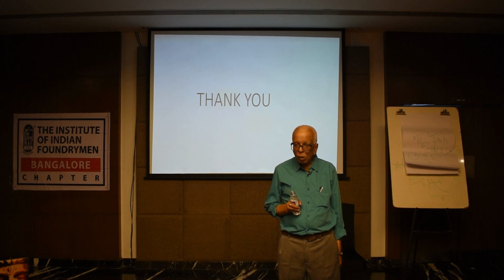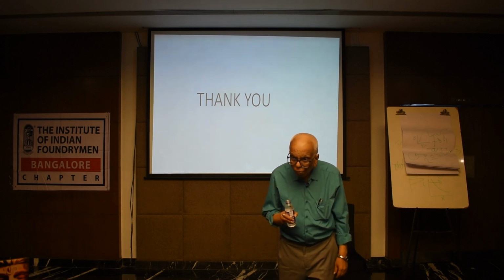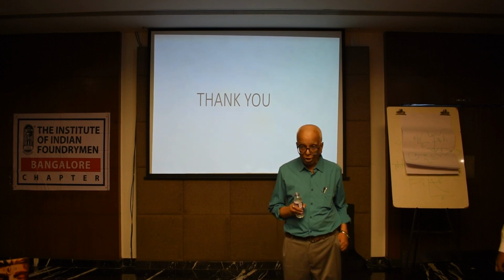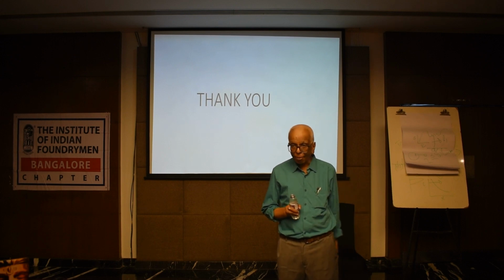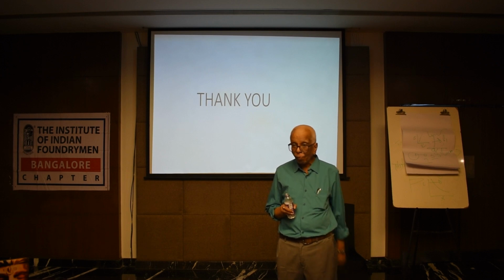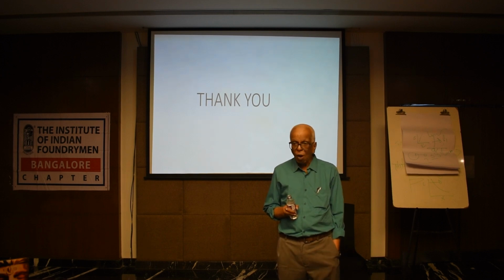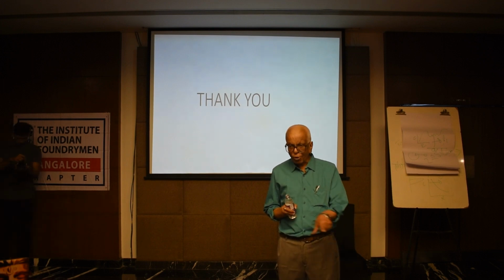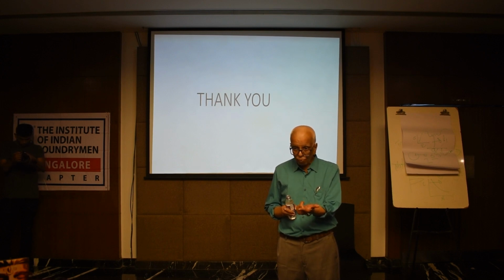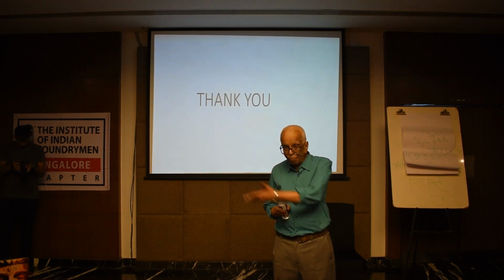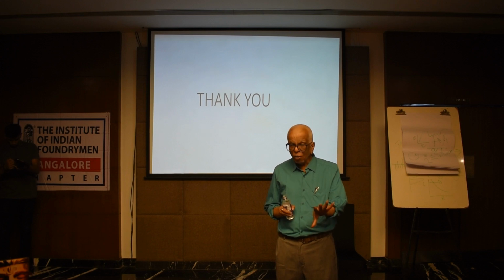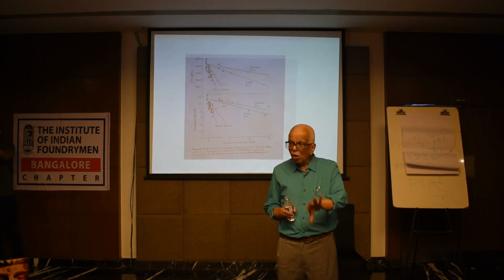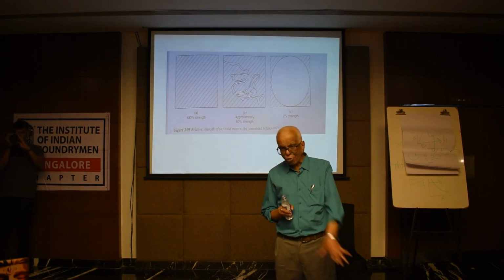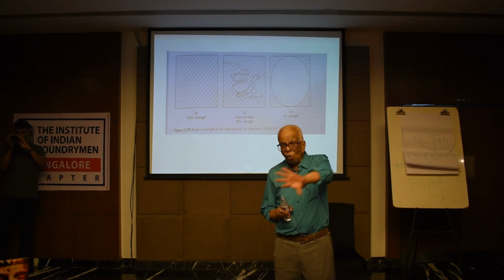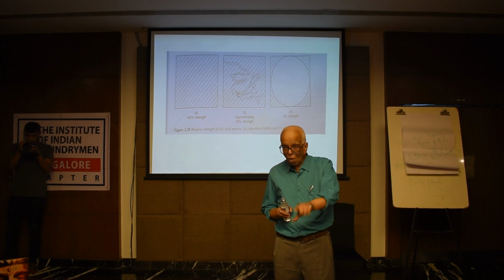Is the phenomenon observed in copper alloys? Yes, copper oxide folds up in copper alloys. Basically, oxide folding is the problem, particularly in the pressurized gating system, because of turbulence in the pressurized system. A 1:4:4 ratio is a classic pressurized system. The fluid flow is laminar or turbulent. If you have a Reynolds number below 2,400, it is laminar. When you have a Reynolds number greater than 2,400, it's turbulent flow. When you have turbulent flow, there are a lot of eddy currents in the flow. That forms oxides.